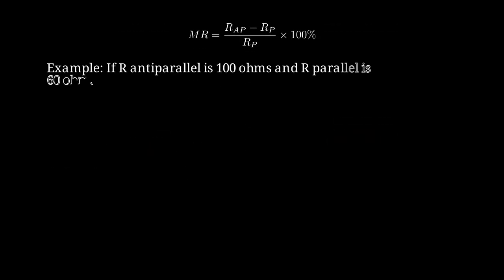Let's work through a concrete example. Suppose we measure R antiparallel as 100 ohms and R parallel as 60 ohms. Then MR equals (100 minus 60) divided by 60, times 100%, which equals 67%. This is a giant effect. So what microscopic mechanism causes this enormous difference in resistance? The answer is spin-dependent scattering at interfaces and within the layers.